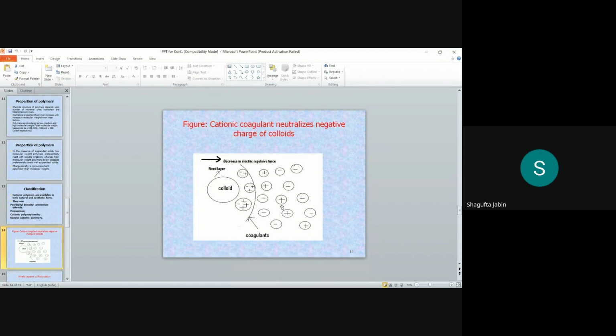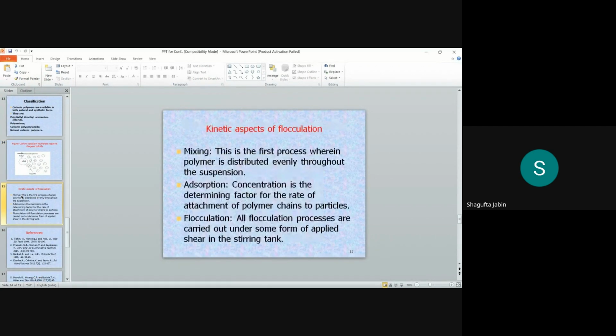For 30 minutes you need to go on with the jar apparatus method, with rotation per minute as follows: in the first minute you take 100 rotations per minute, then decrease to 70 and further decrease to 50, and after half an hour keep it for sedimentation, and then you find the result. You will get tremendously good results, and they undergo the kinetic aspects of flocculation: first mixing, then they get adsorbed on the surface, and flocculation is done.